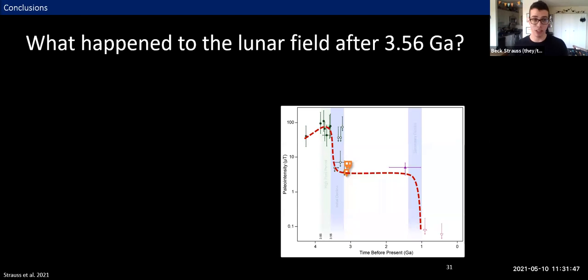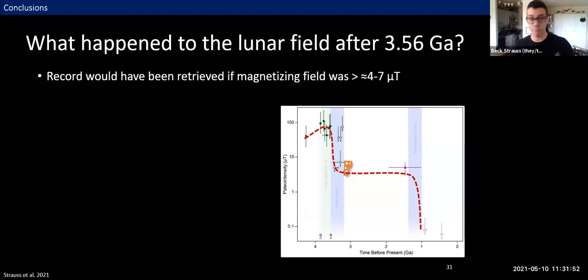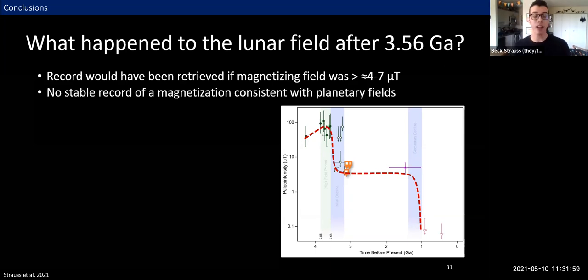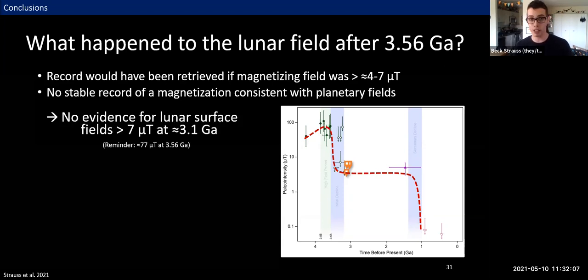Now, this is the part where if you have fallen asleep or been checking your phone anytime in the last 20 minutes or so, I'm going to attempt to summarize the entire talk in under 2 minutes. Here we go. What happened to the lunar field after 3.56 billion years ago, the end of the high field period? Well, our methods would have been able to retrieve a record of the field if it was any stronger than roughly 4 to 7 microtesla. However, we did not retrieve a stable record of a magnetization consistent with that kind of planetary field. Therefore, we find no evidence for lunar surface fields any stronger than 7 microtesla at about 3.1 billion years ago.